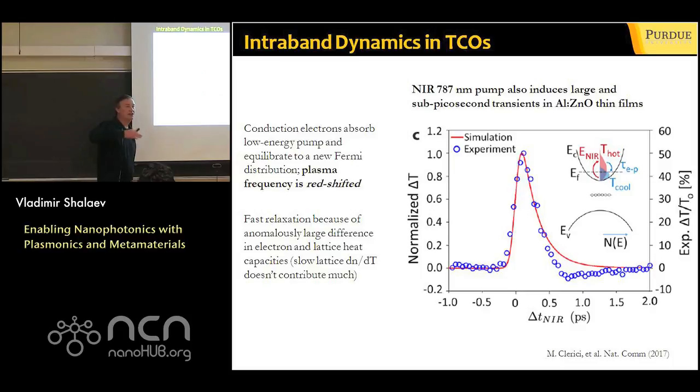You could think of this as a kind of saturation effect, because when you excite electrons below the Fermi level to these upper states, you populate more and more, and there is a saturation effect. Absorption drops eventually. When absorption drops, transmittance increases. So here delta T is positive, here it is negative, which means that if I apply both a UV pump and a near-infrared pump, and they have different signs of nonlinearity, I could design and engineer my nonlinear response. And that's truly a beautiful thing, and that's exactly what we did.